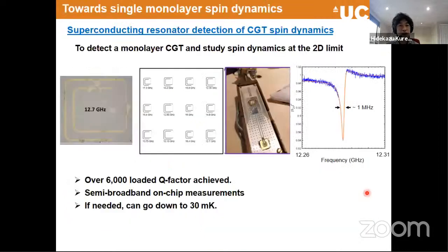That's the reason why we just decided to use the superconducting resonator as a sensing mechanism of this particular kind. This is just a nitride sputter-deposited on this pattern, and this is a particular shape of the resonator. The width of the bar is about a micrometer, similar to the lateral size of this. And this is an inductive coupling regime.